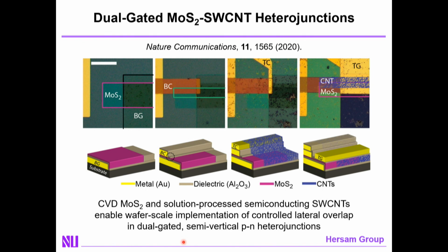And so you can probably guess how we do it. We exploit mixed dimensional heterojunctions. And in particular, the first one I want to introduce is a 2D, 1D mixed dimensional heterojunction between 2D molybdenum disulfide, which is an N-type semiconductor, and 1D carbon nanotubes, which are P-type semiconductors. So this is a PN heterojunction, and it will show a rectifying current voltage curve like a traditional PN junction diode. But what's different about this PN junction diode is that the materials are atomically thin.